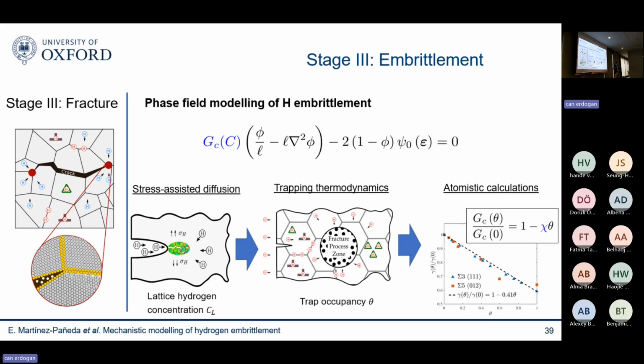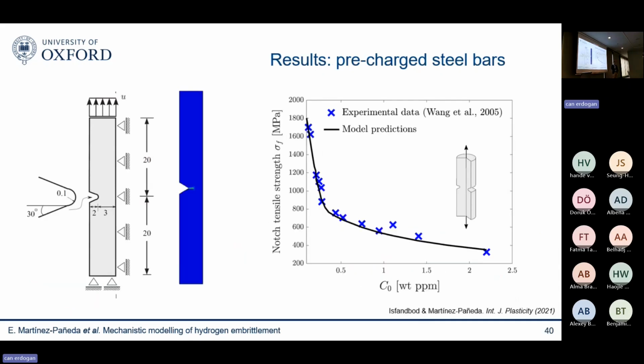And this is straightforward to incorporate into these phase-field models because we are solving a hydrogen transport problem. So we know the hydrogen concentration. Through thermodynamics of trapping, we can relate that to the hydrogen occupancy in the different microstructures in our critical interfaces. And then we just go to atomistics with whatever coverage you have, and we reduce our fracture energy that comes into the phase-field equation. So it's very straightforward to incorporate this. Okay, so let me just tell you some examples of how this model works.